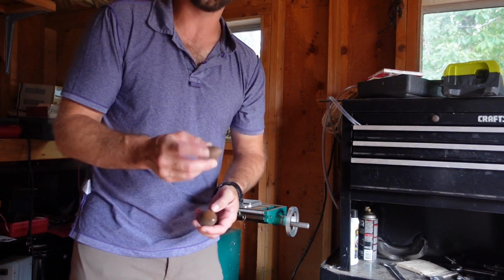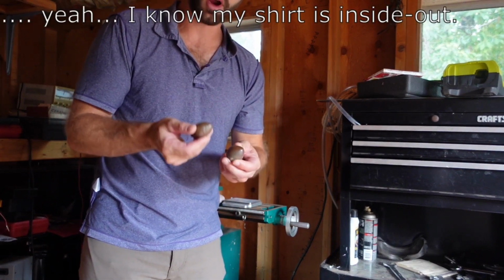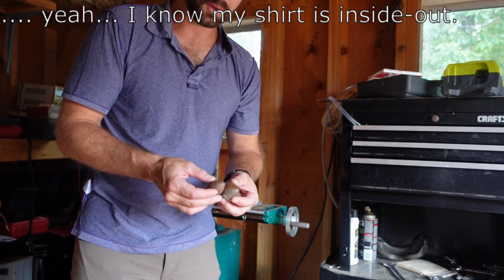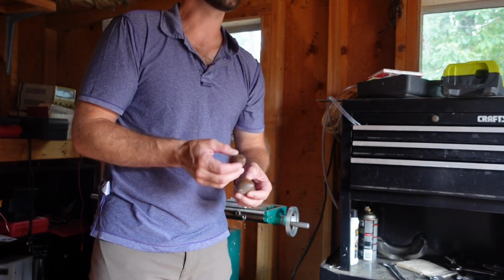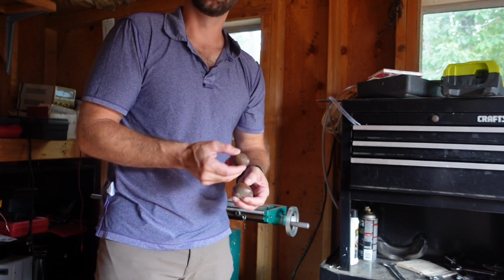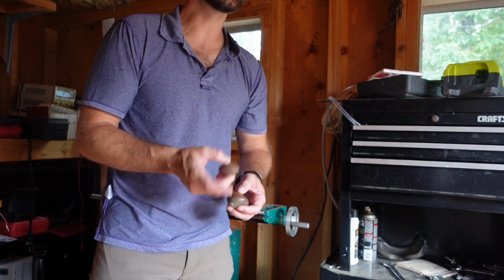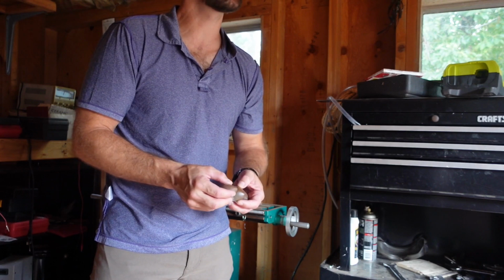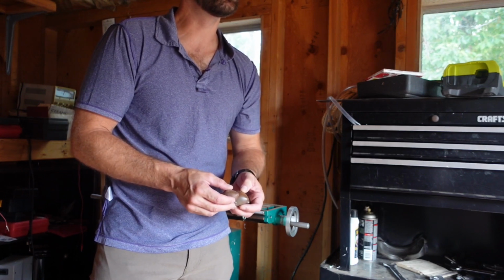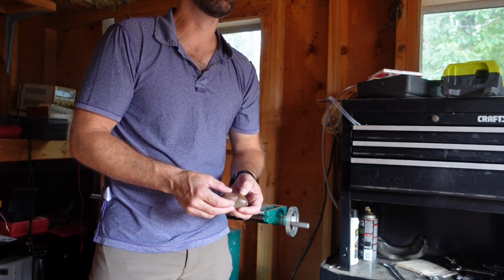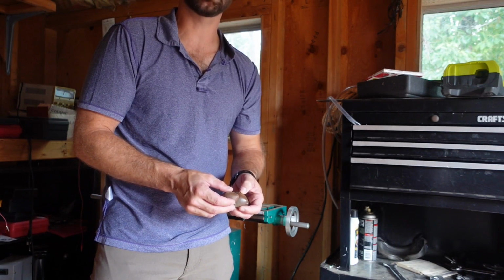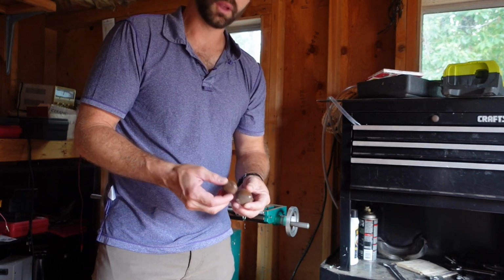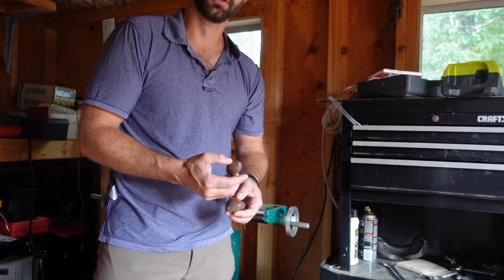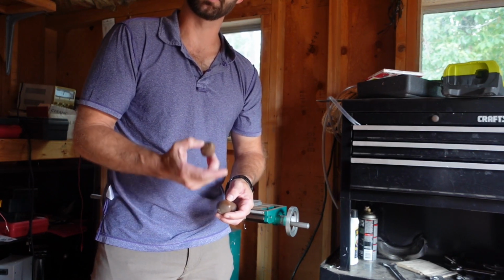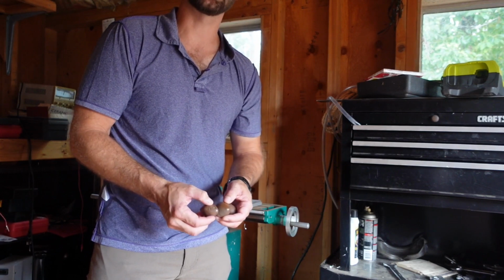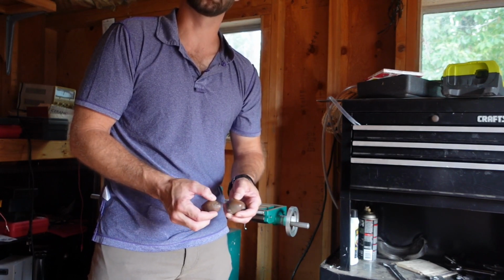That's the key thing, is being able to heat it slow enough so they don't crack, and then get to a high enough temperature. If you look at sintering charts, it depends on the clay, but around 800 Celsius is about the start of sintering, so that's somewhere around 1500 Fahrenheit. And then the sintering starts to melt for a lot of clays around 1200 Celsius, unless it's porcelain. 1200 Celsius is about 2000 Fahrenheit-ish.